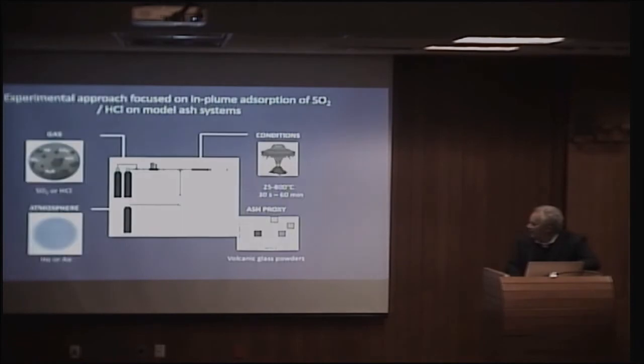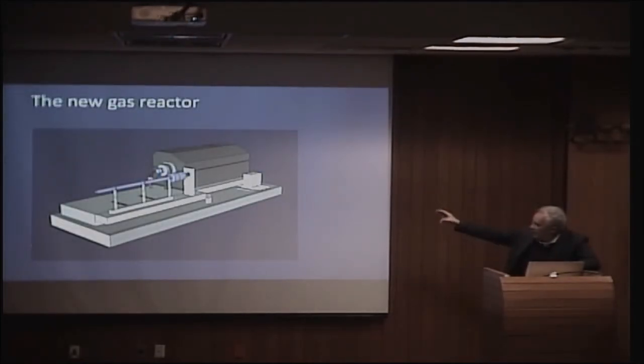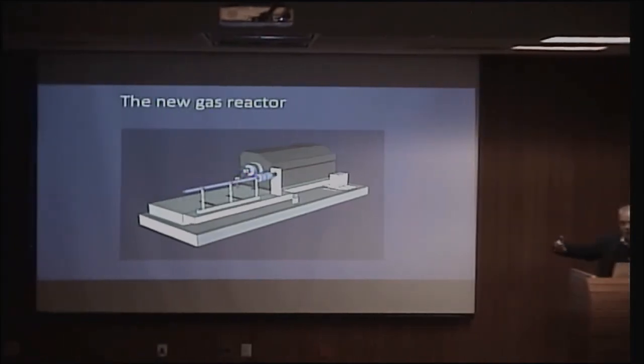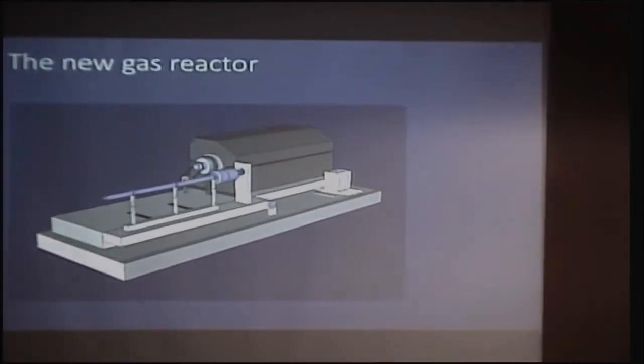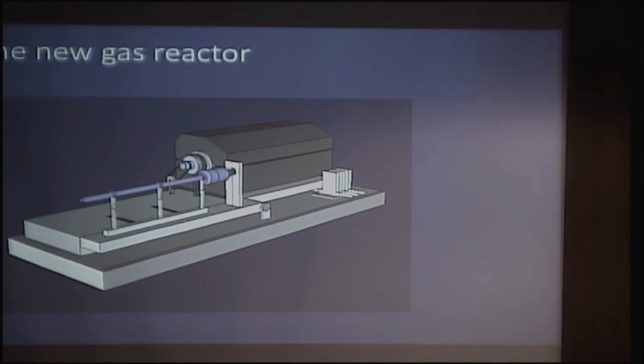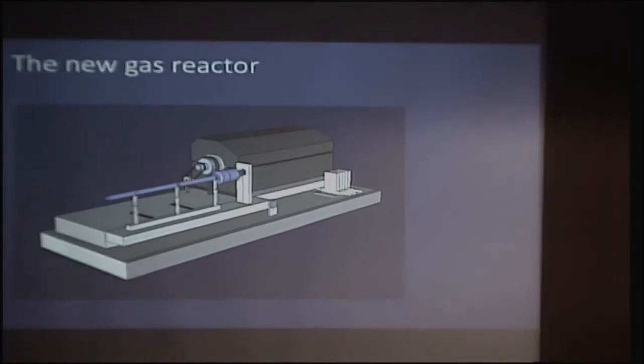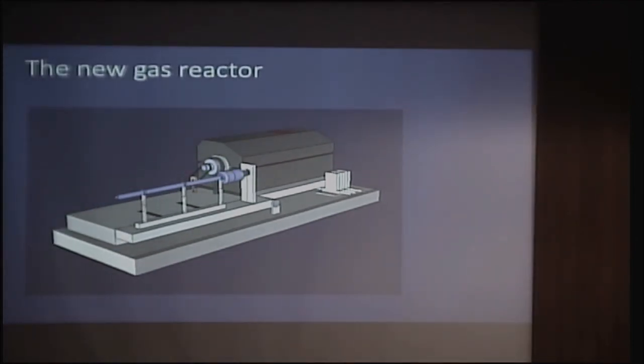Okay. We're doing experiments with something we call a reactor, an ash-gas reactor. Actually, it's Ana Casas who's doing these experiments. She's a good chemist, and she's doing the interaction of powder mixtures, which must be exposed in a reproducible way, their surface, to a reacting gas. So the way you do this is you rotate them in a tumbler. So nothing is being reactively stuck and glued to each other. There's no loss of permeability of that powder sample. It remains in its initial particulate form, the simple mechanical trick of tumbling it. There's no fragmentation in the tumbling, or at least we hope.